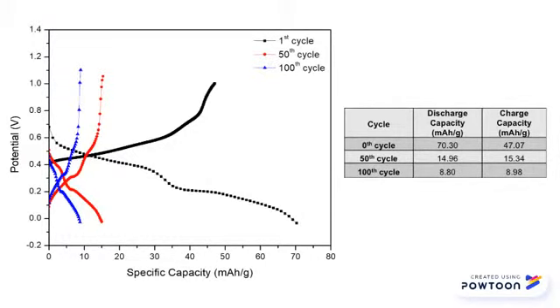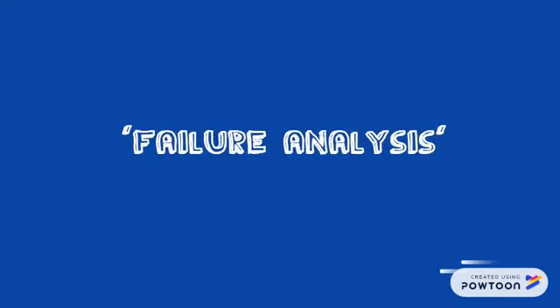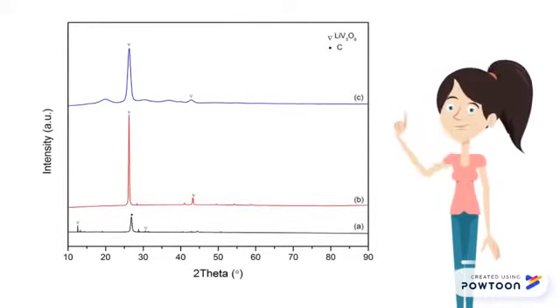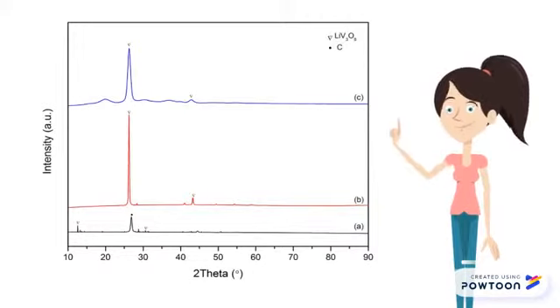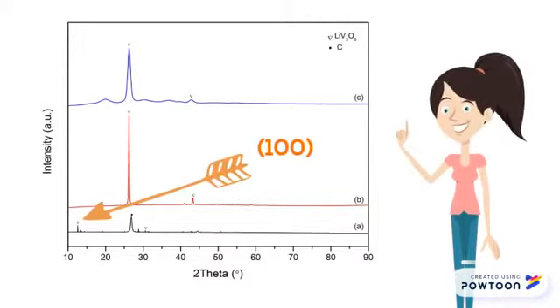According to the journal, byproducts from the charging and discharging process will form on the anode, such as the solid electrolyte interface. It competes with reversible lithium intercalation, promoting a large resistance at the interface. This is one of the reasons leading to capacity fading. As we can see, the XRD patterns of the electrodes are almost similar at 0, 50 and 100 cycles. The significant peak of the LVO anode, 100 in the lattice plane, seems to disappear after cycling. The structural transformation of the vanadate is a main cause of capacity fading.